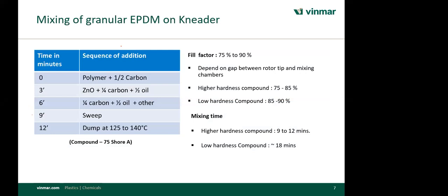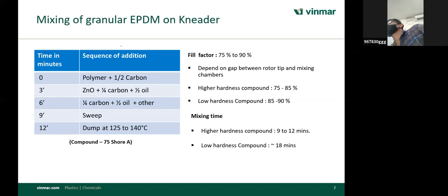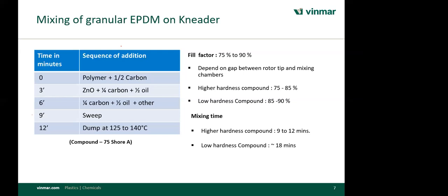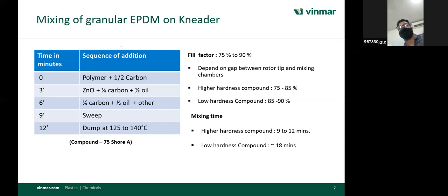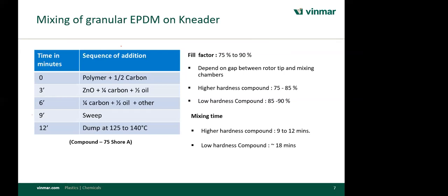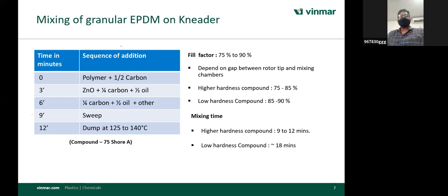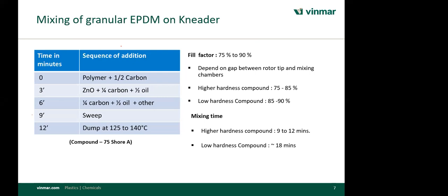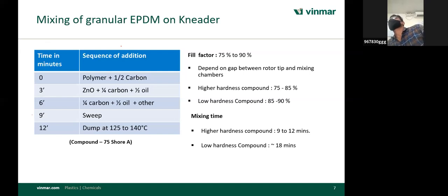Mixing sequence of the granule EPDM. Nowadays you will find a lot of EPDMs come in granule form. So mixing is very important to get the properties for granular EPDM. Earlier, when EPDM was coming in bale form, people didn't have any mixing problems, and they used to mix like other synthetic rubbers. But for granular EPDM, we recommend dry mixing. It means you mix the polymer and half of the carbon black at time 0 and mix for 3 minutes. So this is the dry mixing.